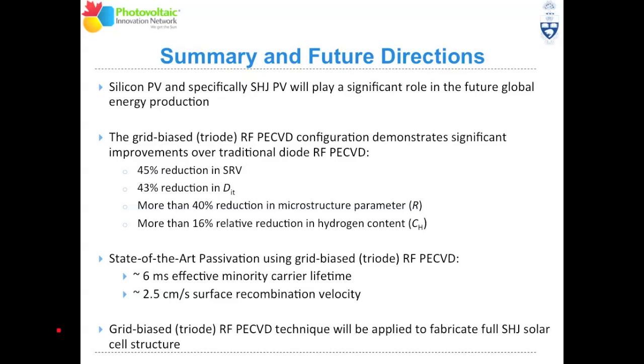This is amongst the best reported in the literature for crystalline silicon solar cells, where I wrote here 6 milliseconds, but actually more recently we've achieved above 7 millisecond minority carrier lifetime in the crystalline silicon wafer, and below 2.5 centimeters per second in terms of the surface recombination velocity. We are now applying this method in fabricating full silicon heterojunction solar cells, and all the results we've achieved thus far really point towards really excellent results. So it'll be interesting to see once we complete those cells.